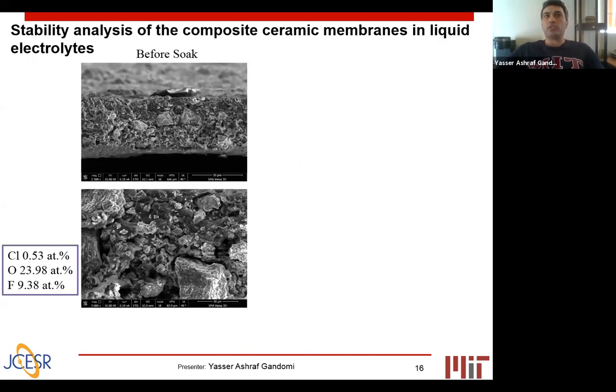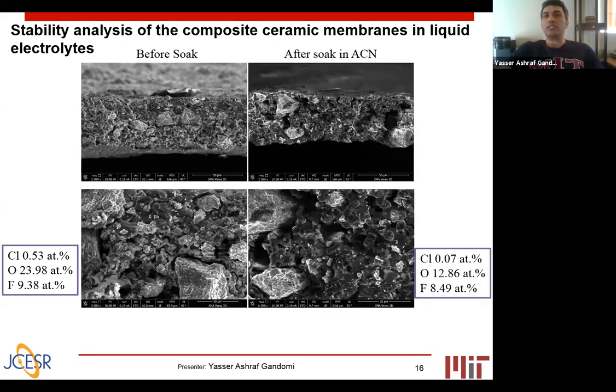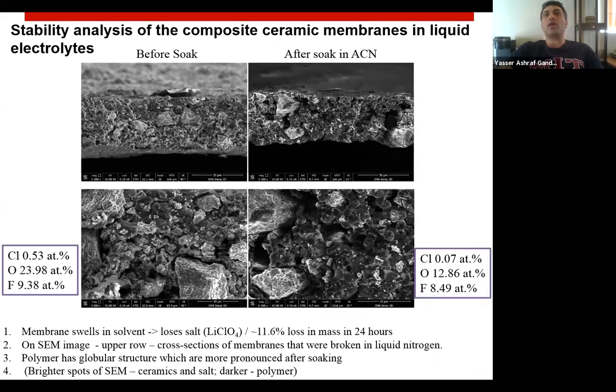It was also important to make sure that the stability of these membranes is maintained. So what I'm showing here are the SEM images of the composite membranes before soaking them in a solution containing acetonitrile. On the right, you see the SEM images after the soak. It's very clear that after the soak, we see wide, large voids within the structure. And comparing the elemental composition before and after, it's clear that we have lost Cl, O, and F after soaking. Almost more than 10% of the mass was lost, and it's mostly the salt, or lithium perchlorate. So the salt is being rejected after we soak these membranes within the acetonitrile.